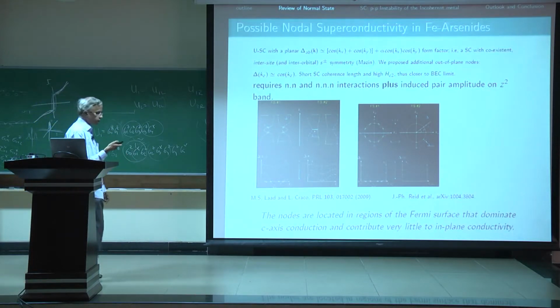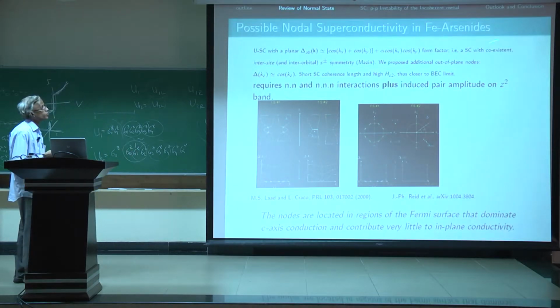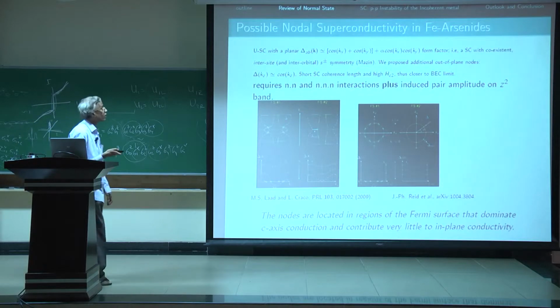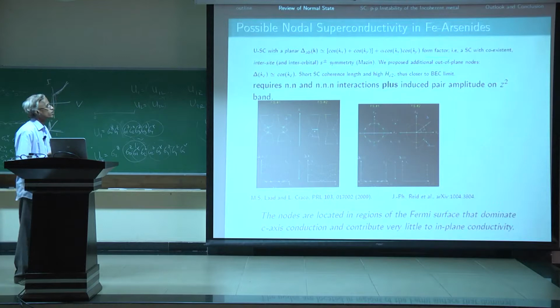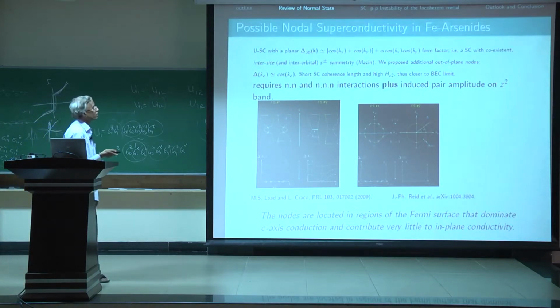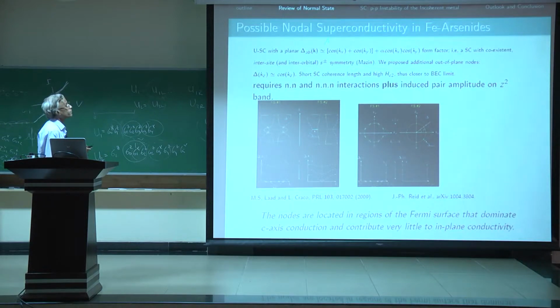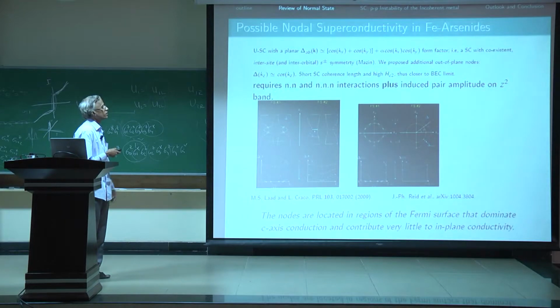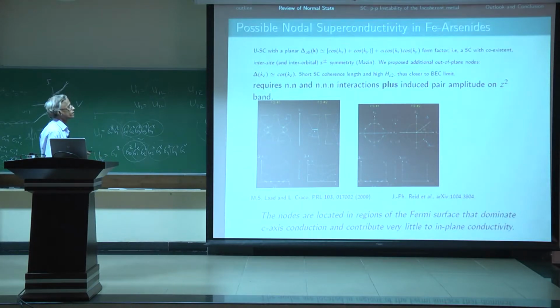But this is not all, because the high upper critical fields in iron arsenides also tell you that the superconducting coherence length is short. So one is not really close to a BCS regime, but rather closer to a BEC limit. Further, this form factor of the effective pairing interaction suggests that basically you have renormalized residual nearest and next nearest neighbor interactions, plus a proximity-induced pair amplitude on the z-square band, which might be relevant.